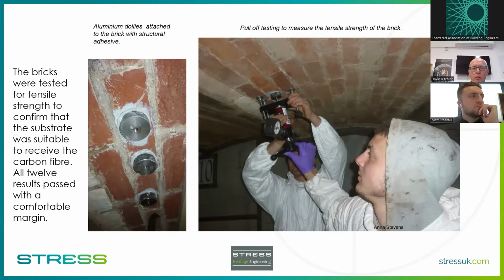1.25 newtons per millimetre square. Won't mean a huge amount, but that's what you require. So you put these little 50 mil diameter dollies on, you glue them on the surface, you let the glue go off, and then you try pulling them off, and you record the level of force required to pull them off, and that gives you your bond strength.